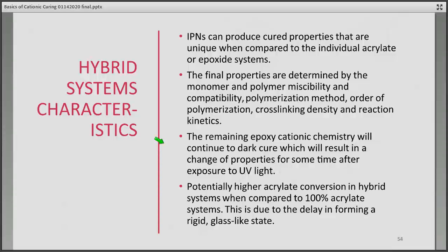The remaining epoxy cationic chemistry will continue to dark cure. So after you form your IPN, the epoxy cationic chemistry will continue its thermal route, and that will result in a change of properties for some time after exposure to UV light. So you will have this shifting of properties. Many times, or even most of the time, that's actually preferred. That's a good thing to get to your final properties. So dark cure does not go away.